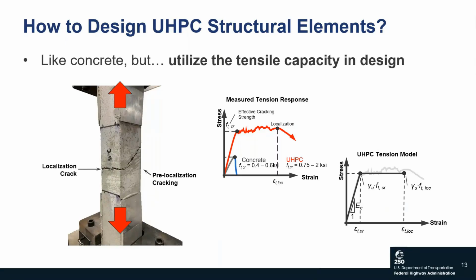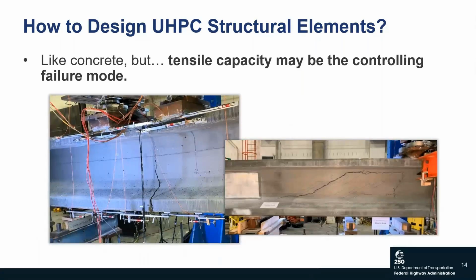The way we do that is by utilizing a new mechanical model in tension that describes the behavior of the UHPC in tension. Generally, that model mimics the stress-strain response that you obtain from a direct tension test. So it is an elastic-plastic model, and I want to point out that it does stop right at the point of crack localization. That is the point beyond which you will start seeing a drop in tensile stress. So you start to lose that bridging capacity of the UHPC and the load starts to drop in tension. That is the point where the model would stop. You design UHPC just like concrete, but now with the introduction of the tensile capacity in the design, a new failure mode will need to be checked, and that's related to the loss of the tensile capacity.